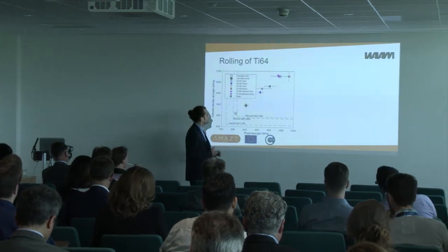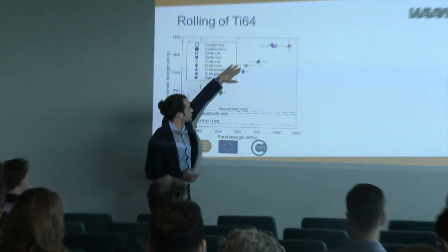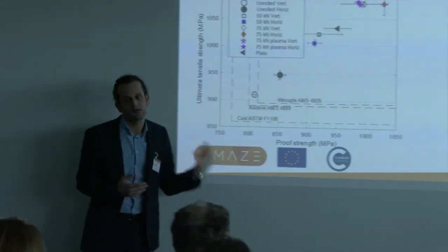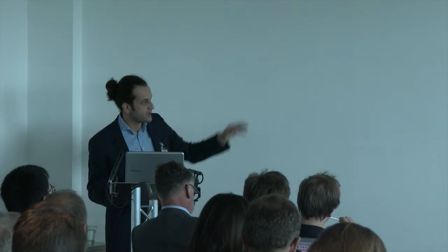And the other thing you can notice is that the points are much closer to each other, which suggests that indeed the isotropic microstructure is also resulting in isotropic mechanical properties. So that's in terms of strength, and then of course in terms of elongation, as you know from the Hall-Petch relationship, the elongation goes down as the grain size goes down. Nevertheless, we've got so much room until we go below the limit for the rod products that even with this big drop in elongation, we are still compliant to the standards.